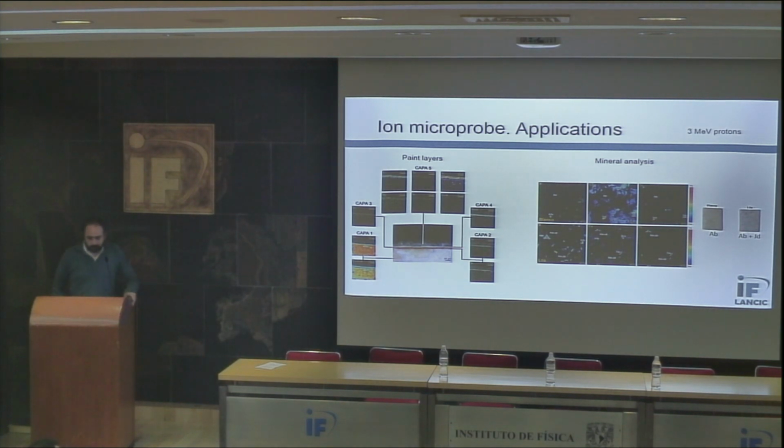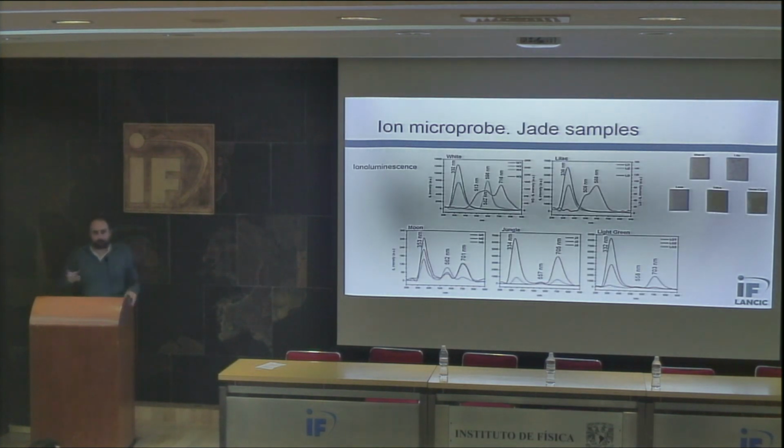Some of the applications, well, the resolution is good enough to characterize painting layers in stratigraphic cuts, and also to do mineral analysis. Like here we have jade samples. And actually with these jade samples, we were trying to observe the composition, including trace elements, in just the jade matrix. We really couldn't find any patterns, but we did find patterns on their luminescence emissions between the different samples analyzed. They did have some characteristic features.